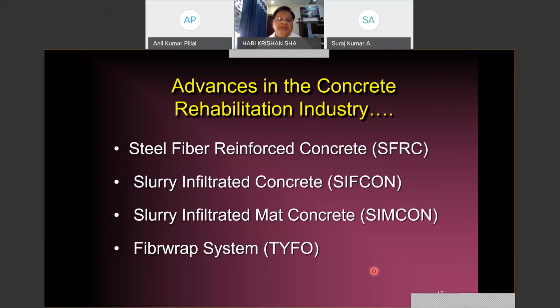All of you, being structural engineers, know that it is a concrete prepared by mixing small discrete steel wires in concrete, and the maximum amount of these steel fibers which can be added in SFRC is 2%. At 2%, there will not be a significant increase in the load carrying capacity, whether in compression, tension, flexure, or shear. So this kind of concrete, which was developed for the construction of conventional structures as well as for repair and retrofitting of distressed structures, did not work for a long time because the strength enhancement was not significant. Then came into existence what is called the slurry infiltrated concrete, the SIFCON.